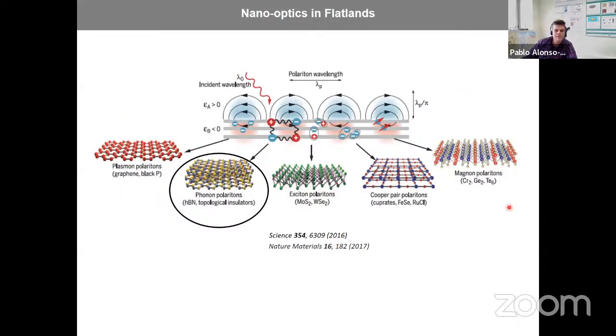Particularly, we have here different families of 2D materials. Here I put a nice review, with the references where they differentiate between, for example, graphene, black phosphorus, and semi-metals, which can support graphene plasmon polaritons. And in this case, because they are thin, you can do field effect, and then you can make active tunability of the graphene plasmons. This is the difference with the bulky systems or noble metal systems that worked before. And this was really a great advance in polaritonics or in nano-optics.